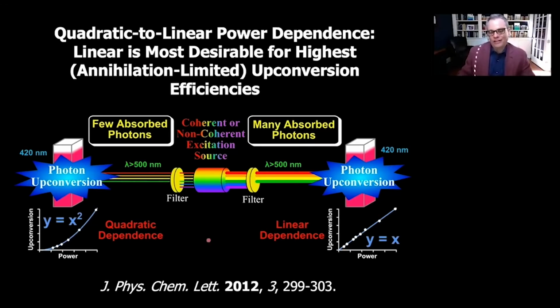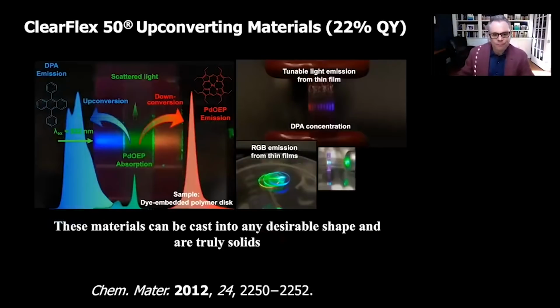And then we recognized, well, if we want to be as high efficiency as possible, we have to get the processes linear, but we have to get a lot of photons absorbed. And if we're using non-coherent light, we have to up the sensitizer concentration. So that was a paradigm shift in my research group, around this time where we recognized we have to change how we do things. And ultimately, that led to new upconverting materials where we can get quantum yields over 20%.